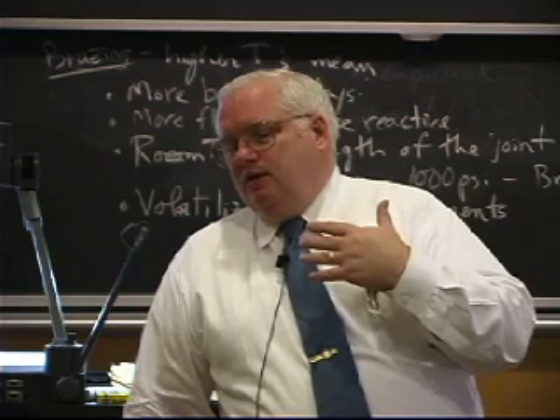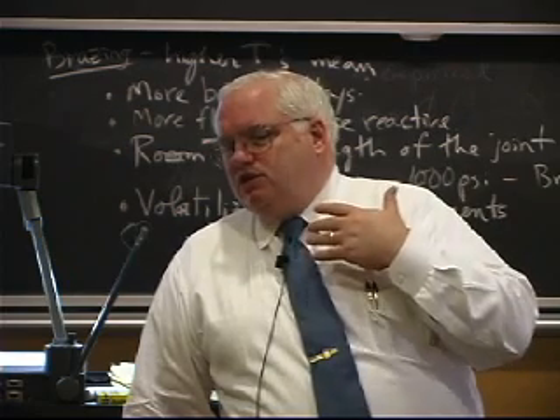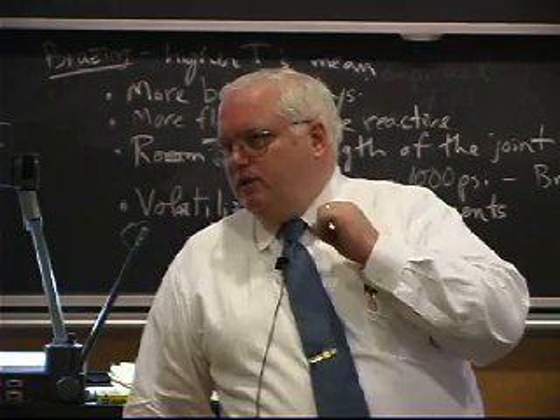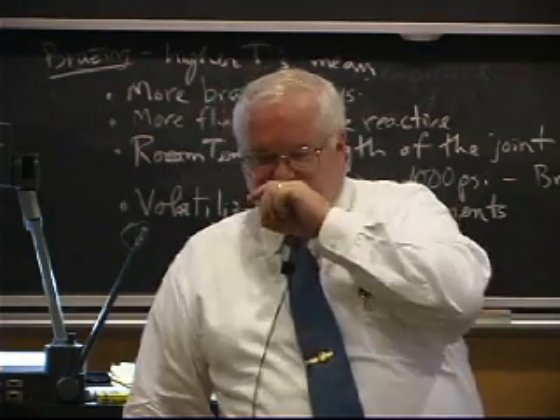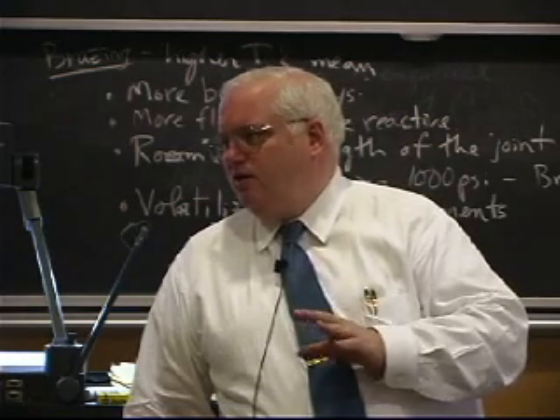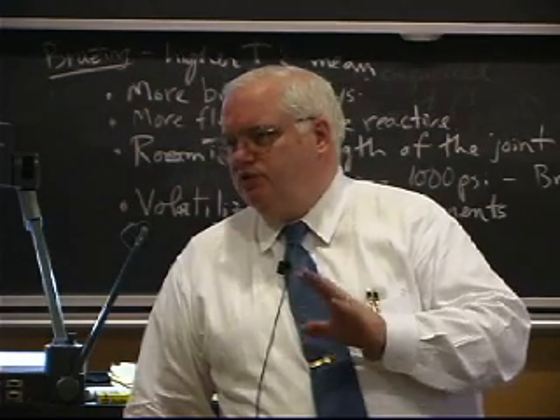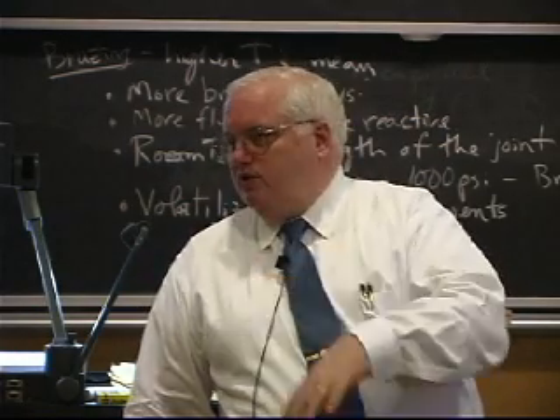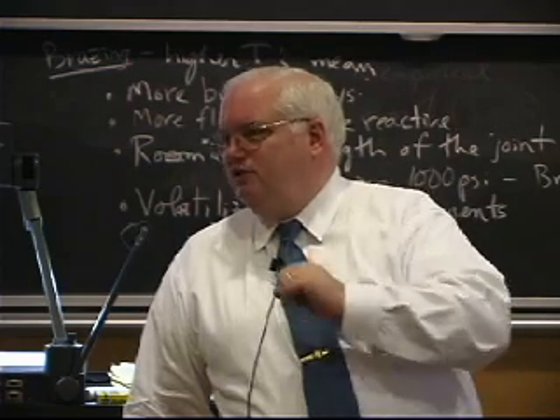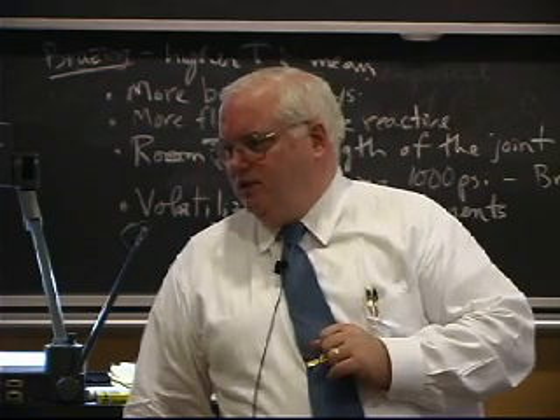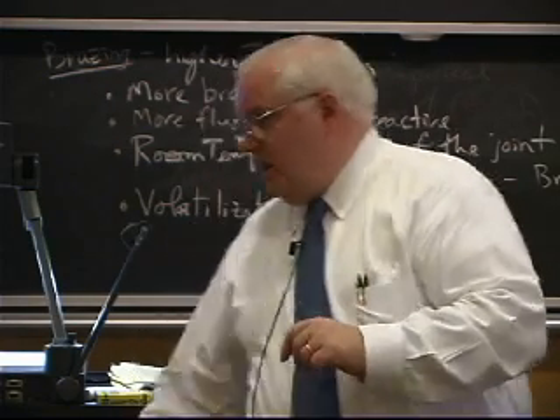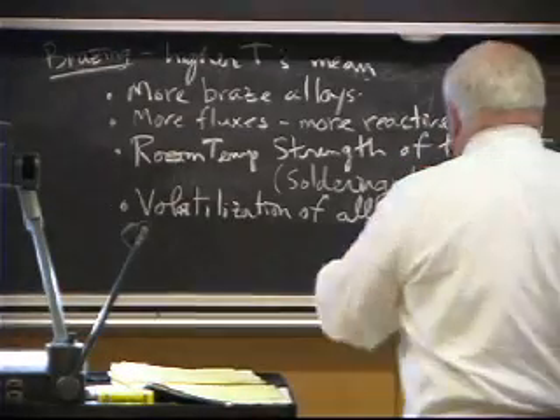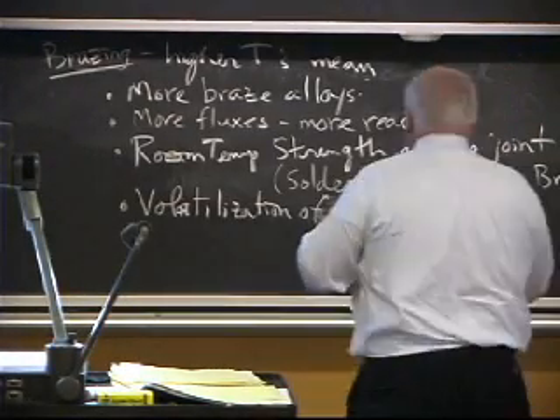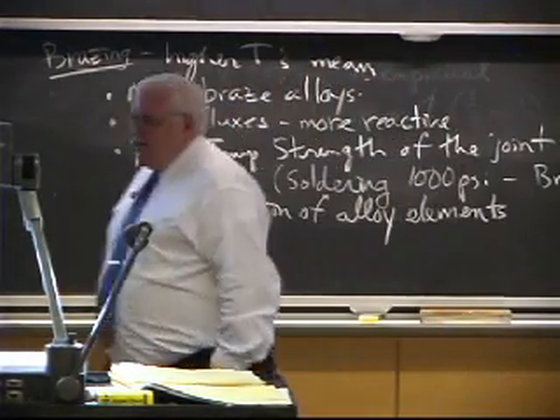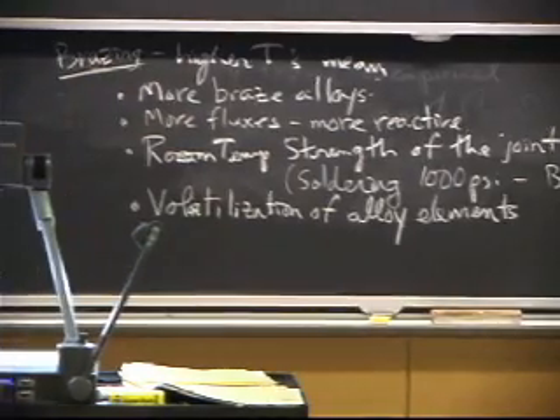But in fact, cadmium just lowers the melting point, improves the flow, just has all kinds of operating characteristics that make it so much better for silver brazing that we actually, in the 1990s, we started seeing an increase again in the amount of cadmium-based silver brazes. We have silver brazes without cadmium, but we're going back to using it a lot. The Swedes were some of the strong environmentalists and wanted to get rid of cadmium.